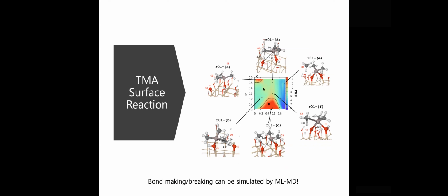Not much of a barrier, meaning that water can easily undergo surface chemical reactions while TMA has some issues. Initially, it would just stick there. It would not make any further chemical reactions on the surface. So extra time or extra energy might be necessary to overcome these barriers.